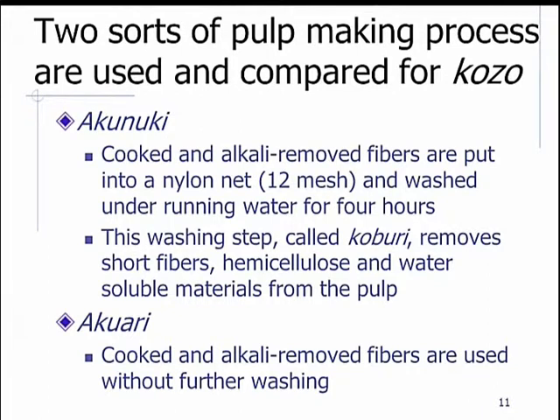In the akunuki process, cooked and alkali removed fibers are put into a nylon net and washed under running water. This washing step removes short fibers, hemicellulose, and water-soluble materials from the pulp. In the akuari process, cooked and alkali removed fibers are used without further washing.